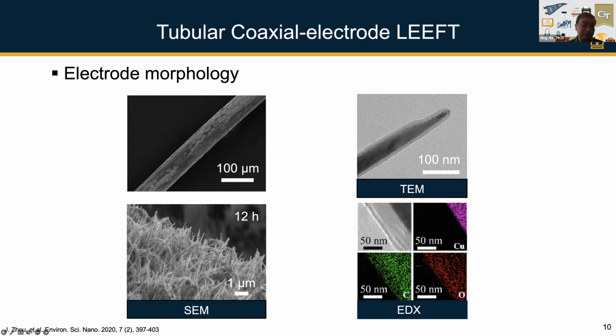And then if you zoom in and look at the features on the surface, you will see there's a lot of these nanowires on the surface, showing these kind of tip structures. And then if you use TEM to enlarge the tips and look at more details about the nanowires, you will see the center, the darker part is the copper oxide nanowire, and then the little bit lighter coating is the polydopamine coating layer outside.